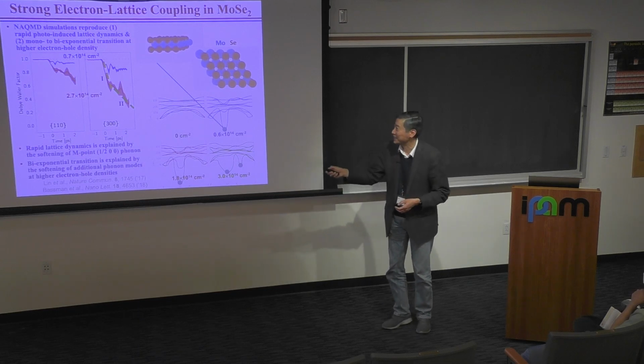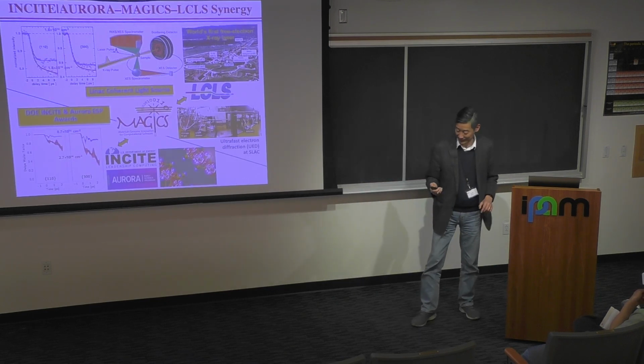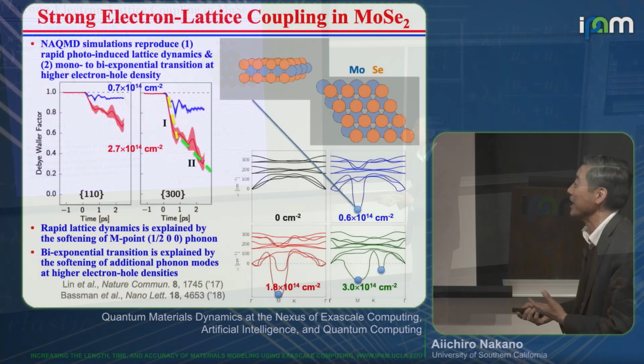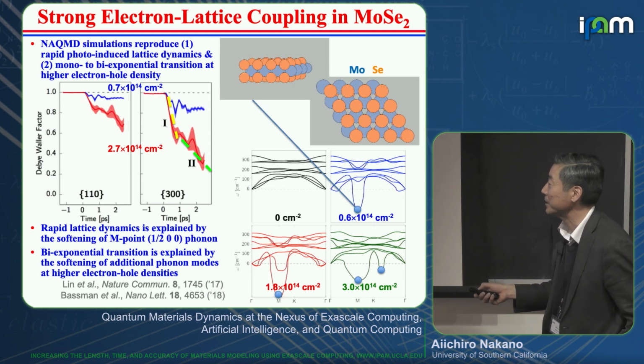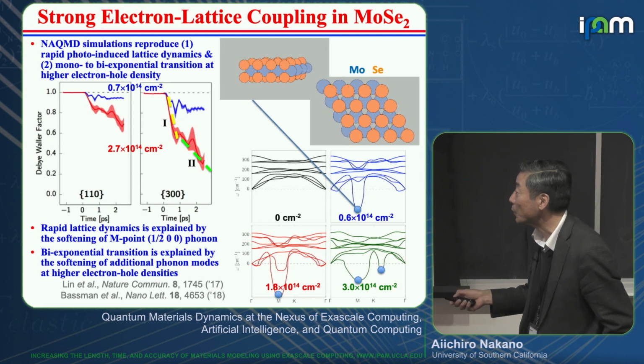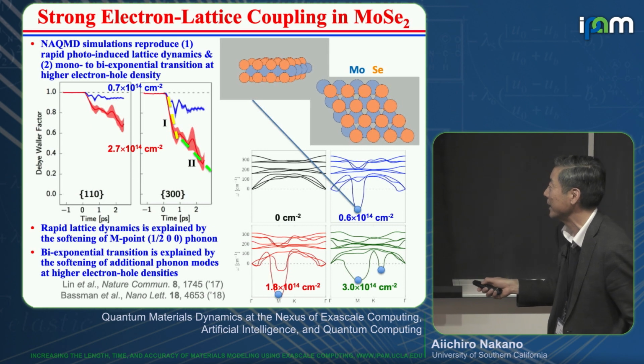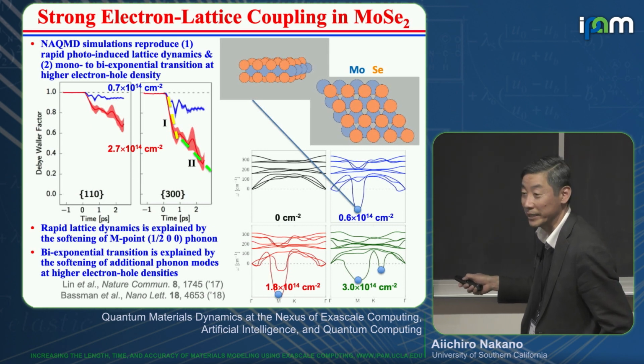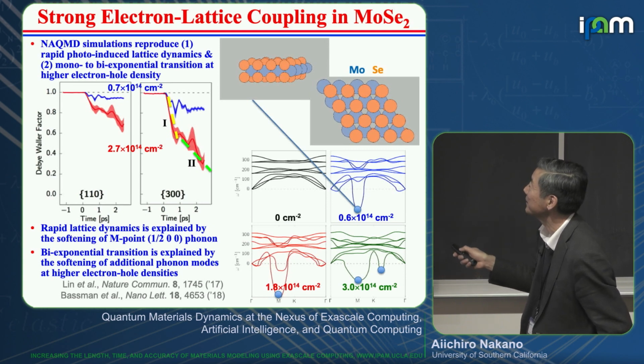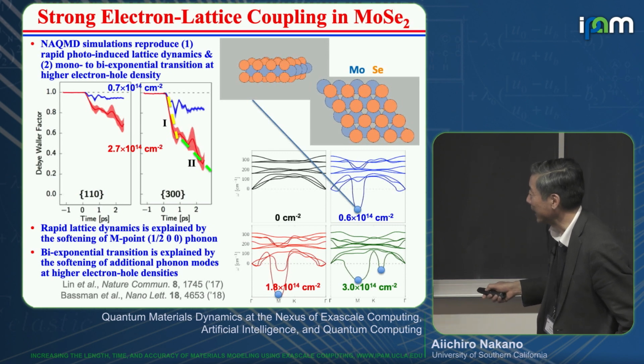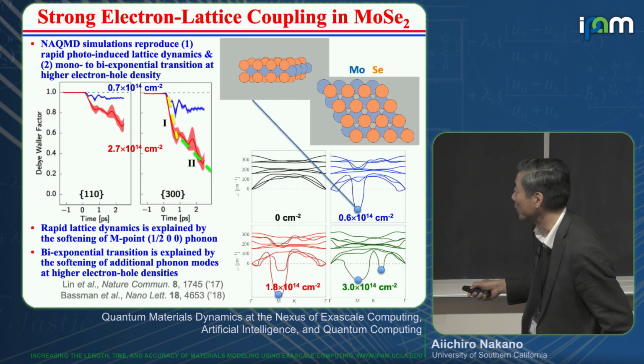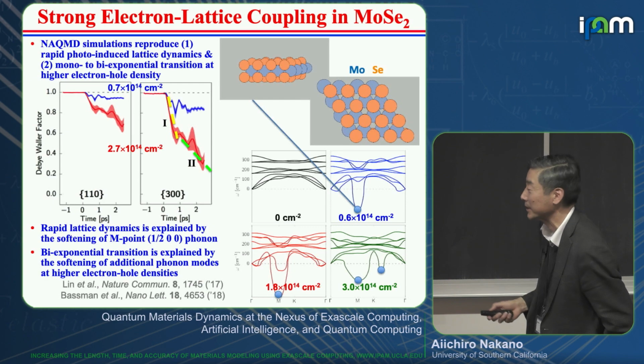dynamics at elevated electron-hole density. This is the low density in blue and then high density in red. And so this is the simulation. Experiment is here, very similar. And then with the simulation, we can explain why it happened. This rapid lattice dynamics in the picosecond was explained as a softening of the M-point phonon. So this shows the phonon dispersion at elevated electron-hole density. We see the softening of the M-point phonon at a certain electron-hole density, and that is reflected in this rapid disorder. And this is the M-point phonon. And then at a higher electron-hole density, another mode is softened that provides an extra decay channel. So you see a different time scale.